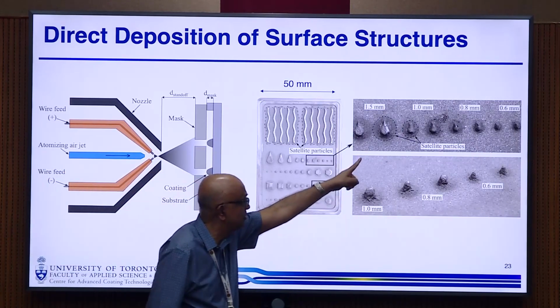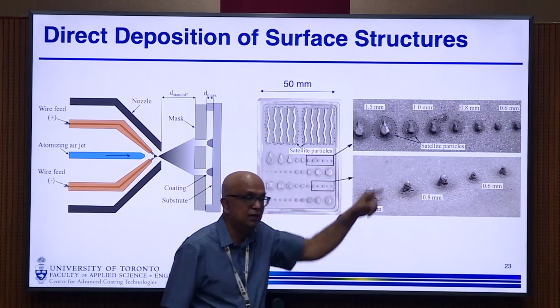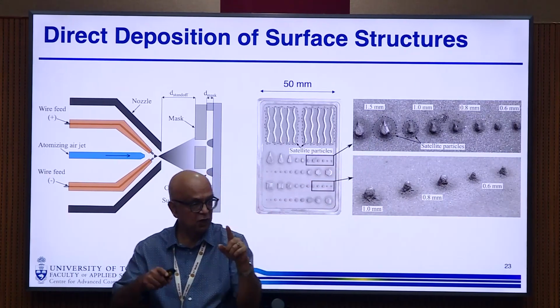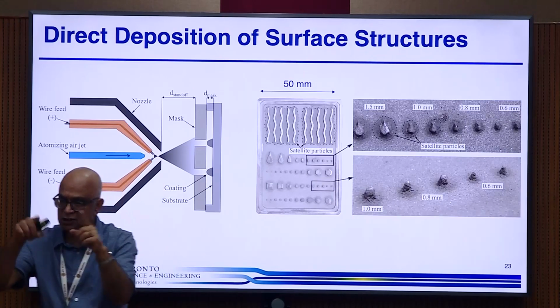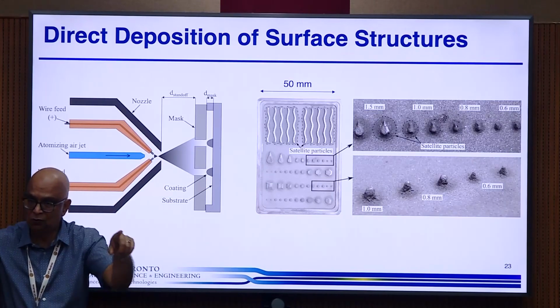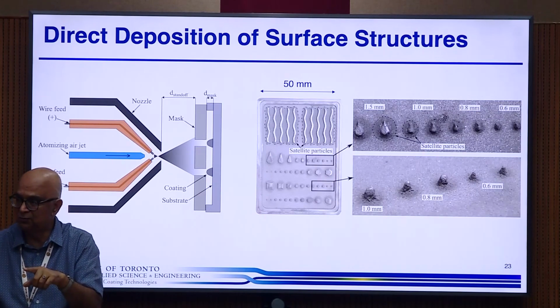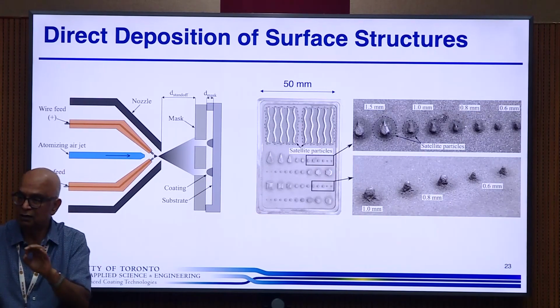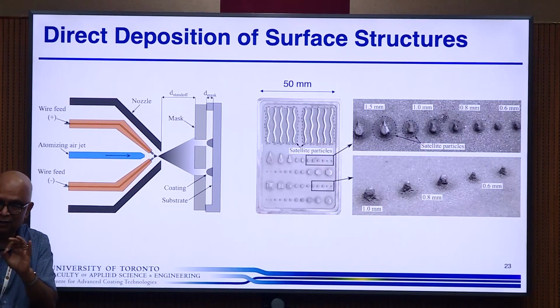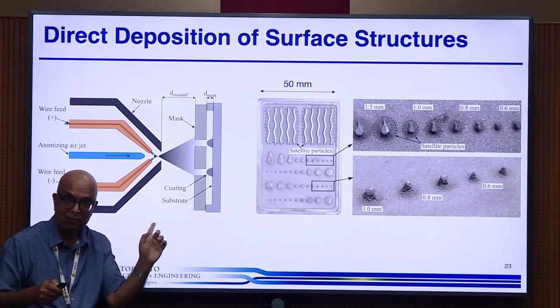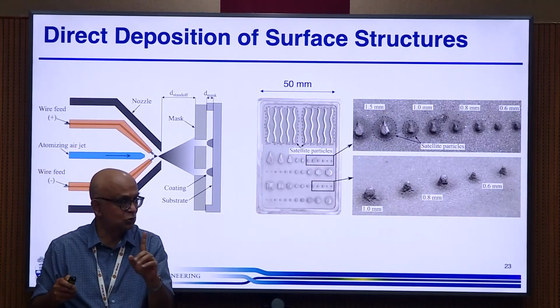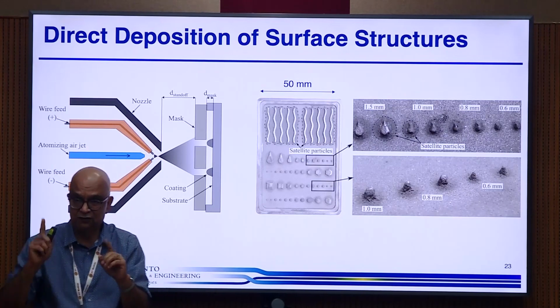One other thing I'll point out, you see around it, these are satellite particles. So if you have an opening in a mask, small satellite particles get through. So all around your structure for a distance of about 1 millimeter, you've got these little particles which have landed. And I'll come back and talk about this because I want to show that this is not actually a bug, it's a feature.